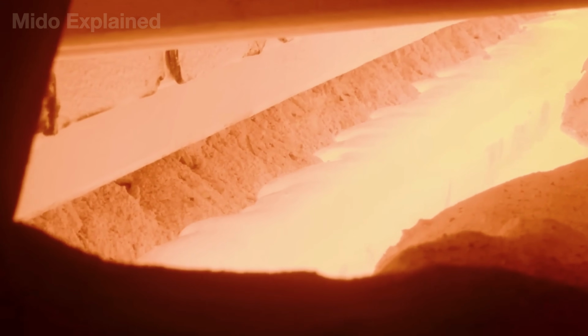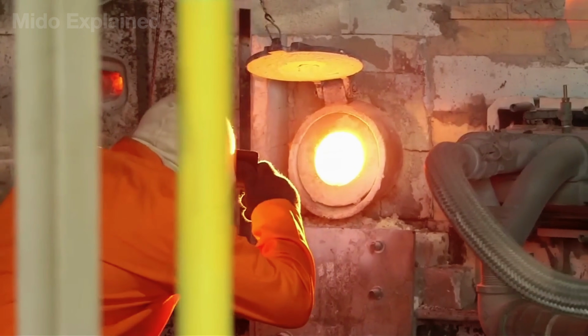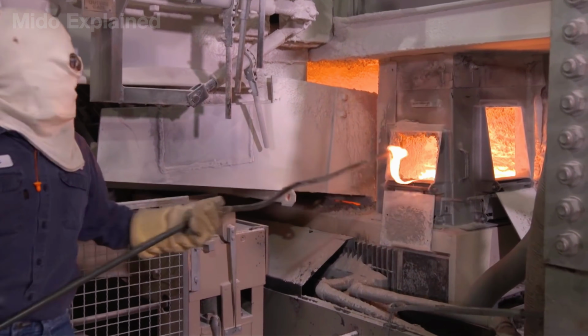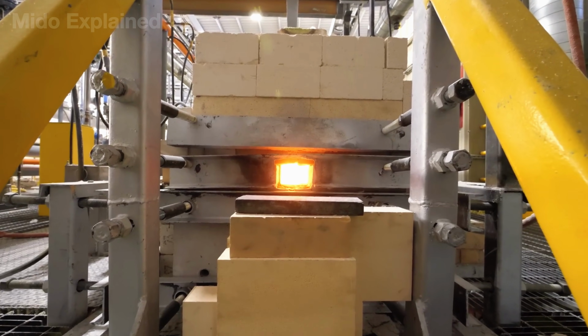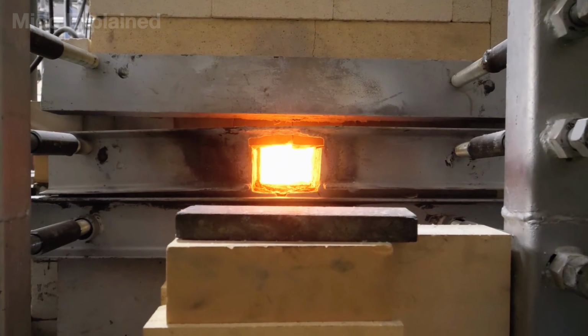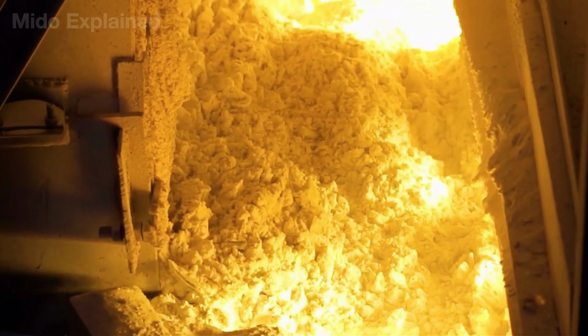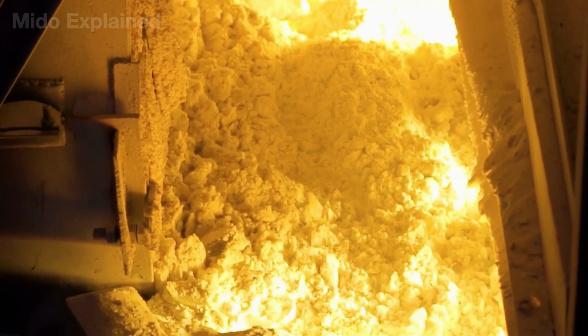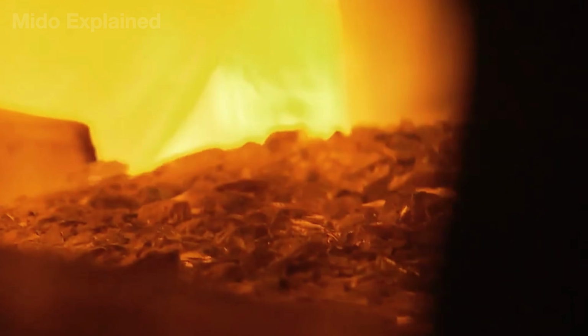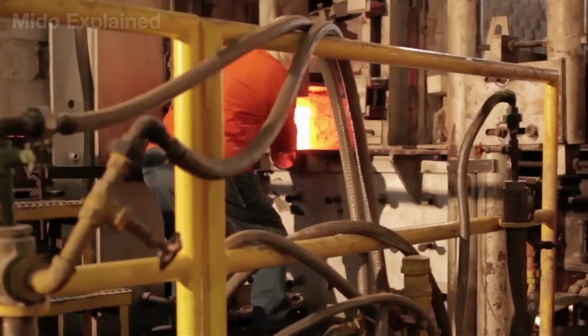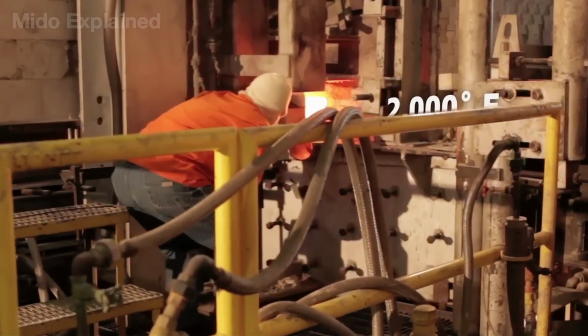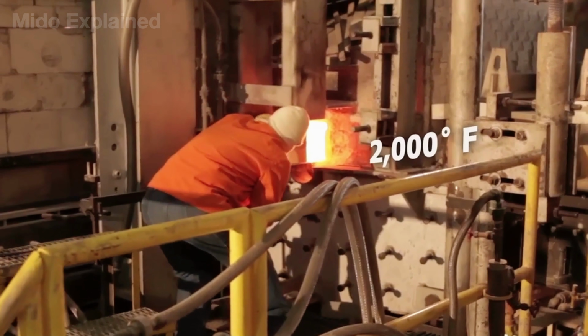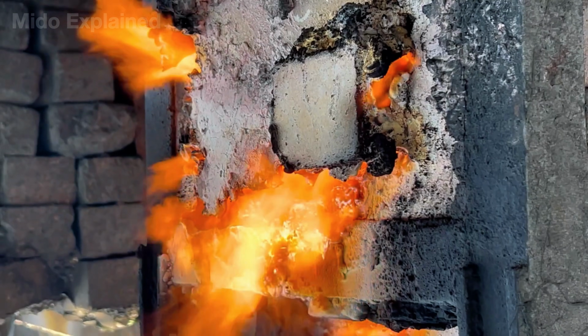The process, spanning from the initial loading of raw materials to the point of complete melting, typically takes about 36 hours. During this time, silica sand, soda ash, and limestone react to form new glass, while air bubbles and microscopic impurities gradually rise to the surface and are removed. The result is a stream of glass characterized by high clarity, a uniform chemical composition, and stable viscosity.